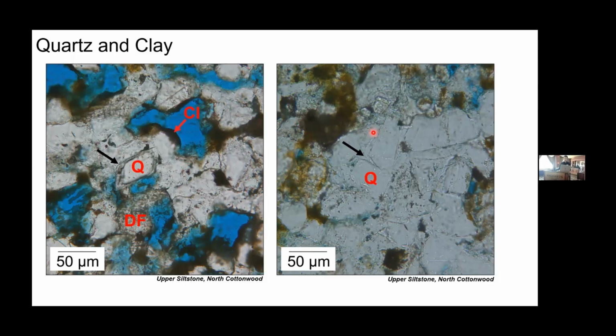In some cases, although it's quite rare, some of these overgrowths can coalesce together and form this patchy quartz cement, shown over here on the right, which completely occludes porosity and results in very little carbonate cement being precipitated in these particular intervals that have a high abundance of quartz cement.